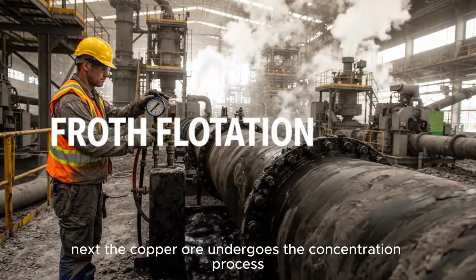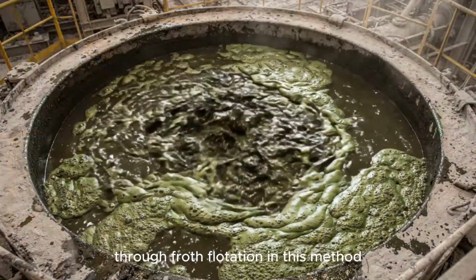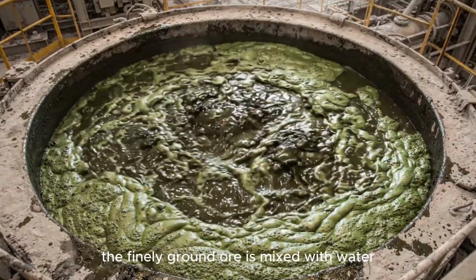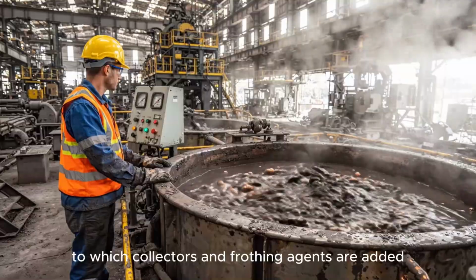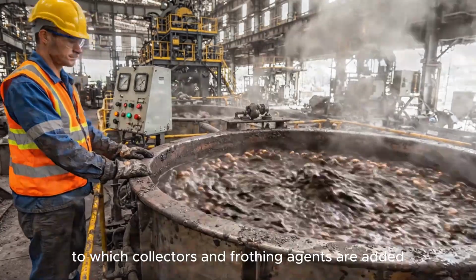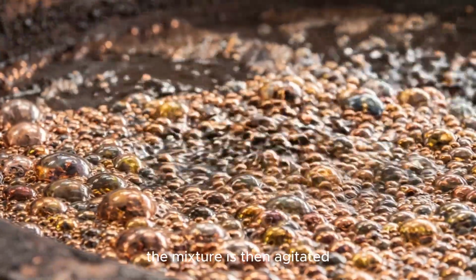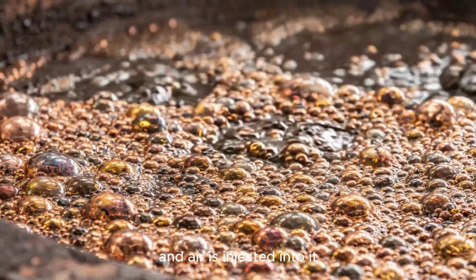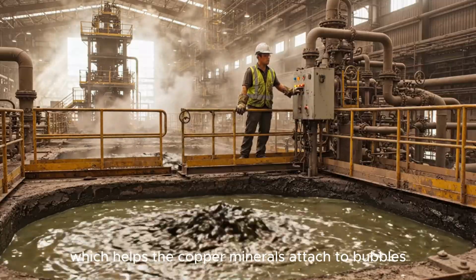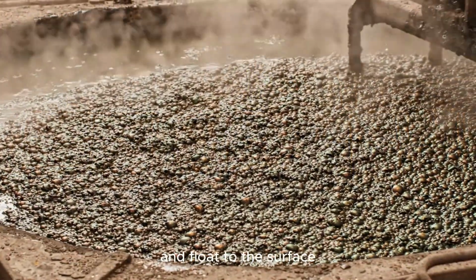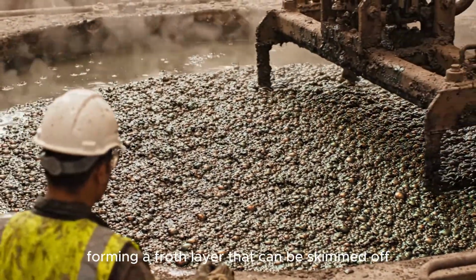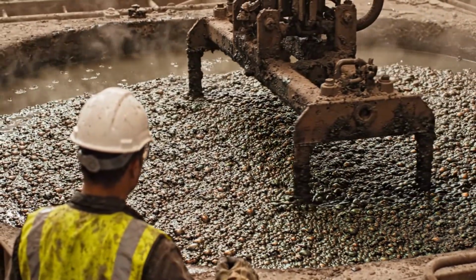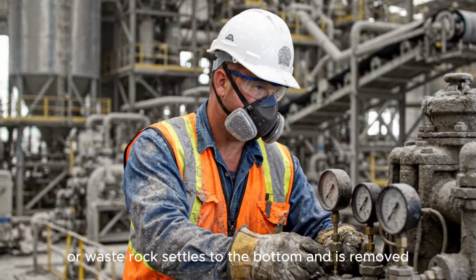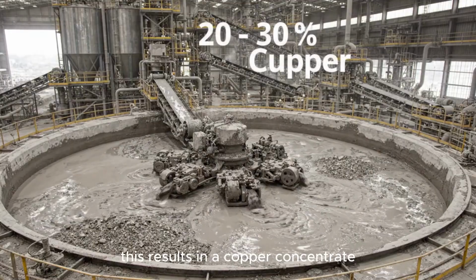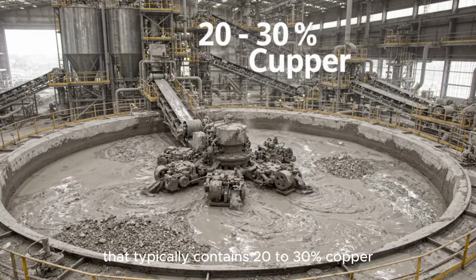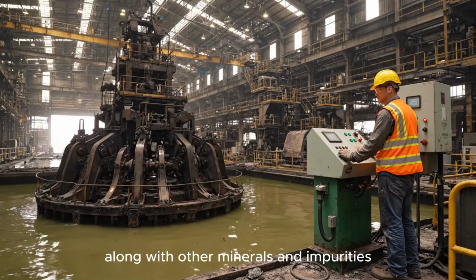Next, the copper ore undergoes the concentration process through froth flotation. In this method, the finely ground ore is mixed with water to form a slurry, to which collectors and frothing agents are added. The mixture is then agitated, and air is injected into it, which helps the copper minerals attach to bubbles and float to the surface, forming a froth layer that can be skimmed off. The gangue, or waste rock, settles to the bottom and is removed. This results in a copper concentrate that typically contains 20 to 30% copper, along with other minerals and impurities.